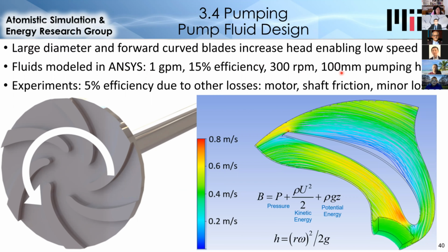develop the 100 millimeters of pumping head needed, although the pump would be operating at very low efficiency because of its low speed. At low speed, a centrifugal pump doesn't have enough velocity for the inertial effects to outrun the viscous losses. So running the pump at higher RPM would resolve this issue. But in fact, the low efficiency, even at the large scale, is not a big issue because the energy density is so high that we can tolerate an inefficient pumping system, around 10% efficiency.